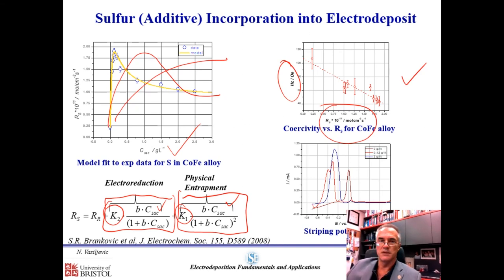However, not necessarily incorporation of additives is a good thing too. It can affect the corrosion properties of the deposit, and here is the example where we use electro-oxidation potential of the cobalt iron deposited with and without additives. Obviously, without additives, the electro-oxidation peak or the stripping peak is the most positive. And with additives, obviously, if you look at the red line, this is the maximum incorporation concentration that results in maximum incorporation, and this is the most negative stripping peak.